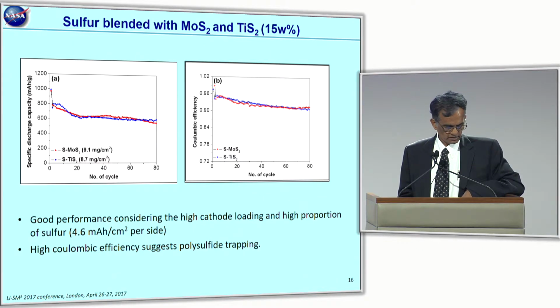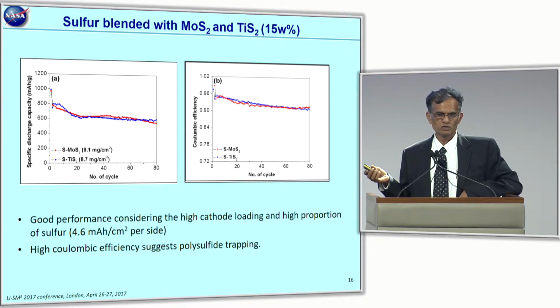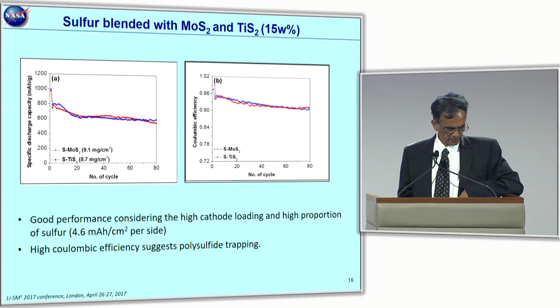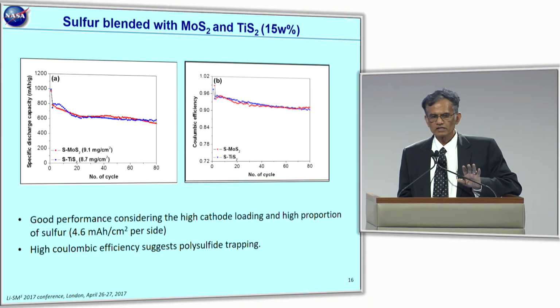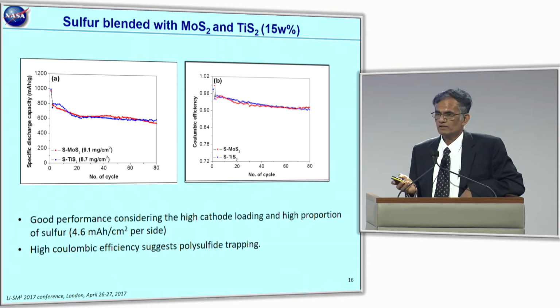Here is data that shows two cases. On the left, we have the TiS2, and keep in mind the loading we are talking about is 9 milligrams per square centimeter, with 85% of sulfur in the cathode. That actually translates to 4.6 milliampere-hour per centimeter square per side. It's only because we're coating the electrodes on one side. So if you look at a typical electrode, we are talking about twice the number, which is pretty high. And more interestingly, compared to a pristine sulfur cathode, we have seen improved Coulombic efficiency with this metal sulfide blended cathode. We are seeing somewhere in the numbers of 95%, even though the electrode is fairly thick.